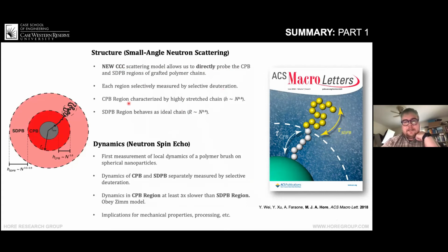So as we expected from theories, the inner concentrated region had highly stretched chains that scaled as n to the 0.8 power, while farther away, the semi-dilute region, or the portion of the chain in the semi-dilute region, had more ideal conformations. Its conformation was more similar to a swollen polymer chain than of a stretched polymer chain.